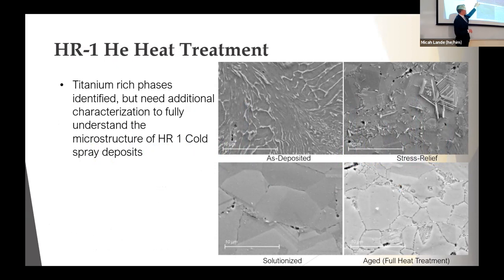This is the same picture as before, where we can see things are pretty plastically deformed and stretched out. As we go into the first heat treatment step, we see those particles are able to reform. Again, they're able to relax. They're able to recreate the expected crystal structure. And then we also see the beginnings of some interesting, very long, very needle-like crystal structure forming.